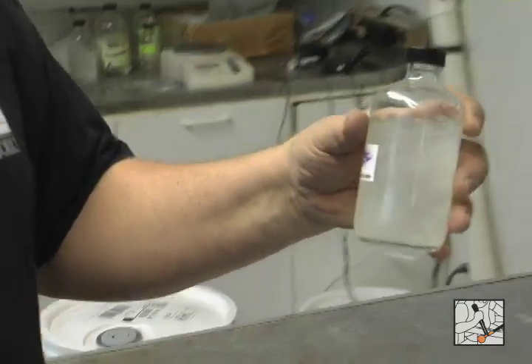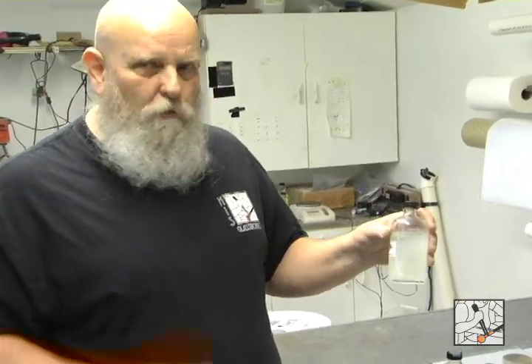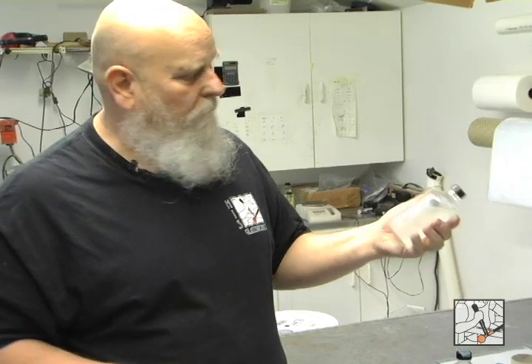Before you use it, the night before or for storage, have it in a place that's approximately 85, 90 degrees. Don't go over 110 or 120. And then part B will be perfectly clear and mixed.